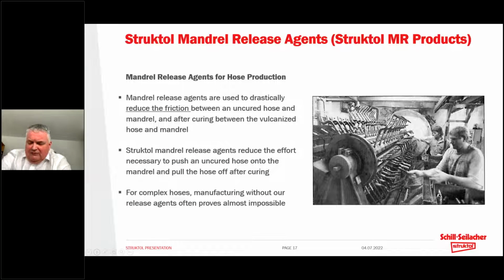So a few words really on the mandrel release agents that are available. Mandrel release agents are lubricants that are designed to allow the shaped hose molding process to run efficiently. Here's a very early photograph of what we're talking about. The uncured hoses must be fitted onto mandrels in order to be cured in the autoclave. We need a lubricant to allow the hose to be pushed on, and later after curing we need the same lubricant to provide the release effect to take the shaped hose away from the mandrel. Next, please.